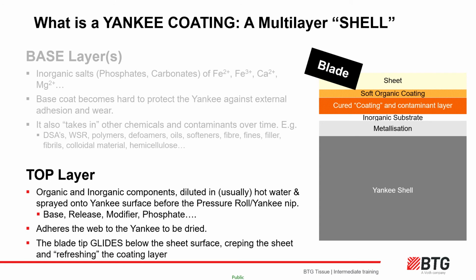Then we have the soft and hopefully robust organic top layer, or coating layer, usually made up of what we see on the previous slide. Base coat or adhesion aid with possibly a built-in modifier, some MAP maybe, and a release agent. Most machines will fix the addition of a base addition and MAP and use the release to control adhesion, stretch and sheet control.